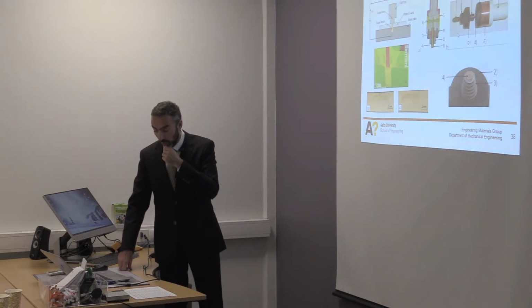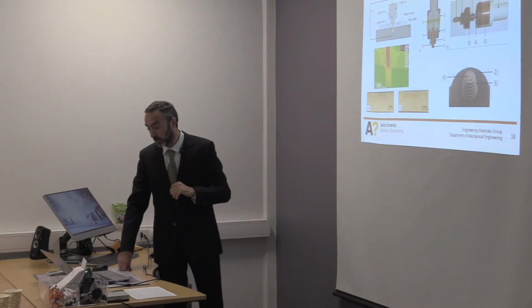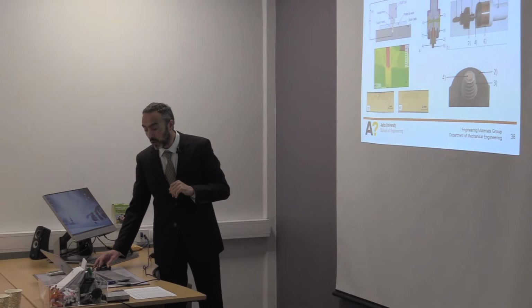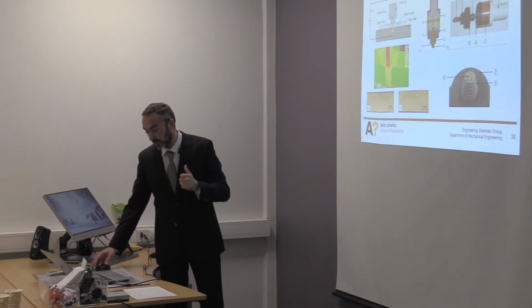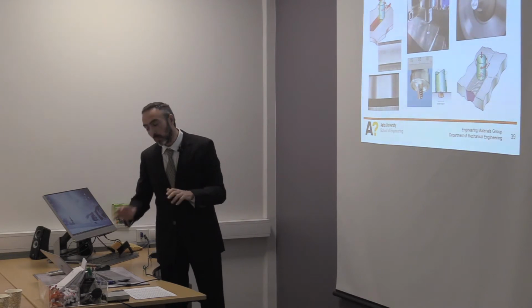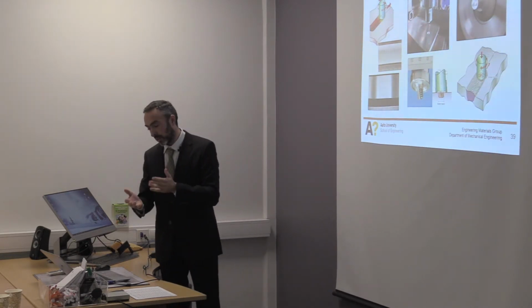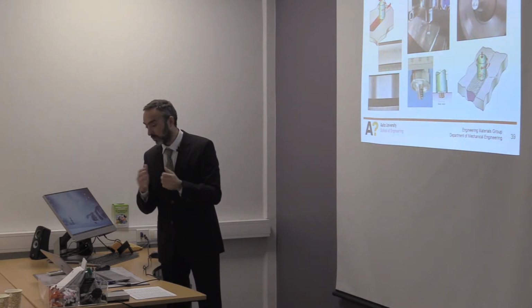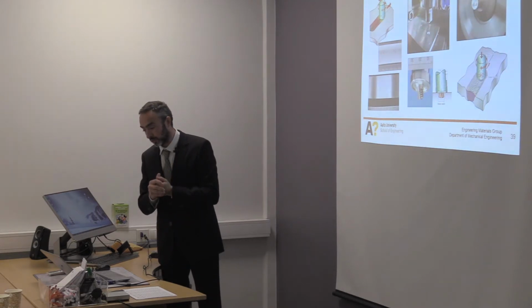Another concept that has been developed in my research group, in cooperation with a research group in Portugal, was this friction stir welding tool assisted by Joule effect, where we are able to overcome the remaining oxide layer at the distance of the tip of the probe to the anvil by processing it with localized heat generation using DC current locally. The complexity of the solution is, on the other hand, the problem of many advanced solutions like hybrid laser welding. Also, the complexity is one of the disadvantages.